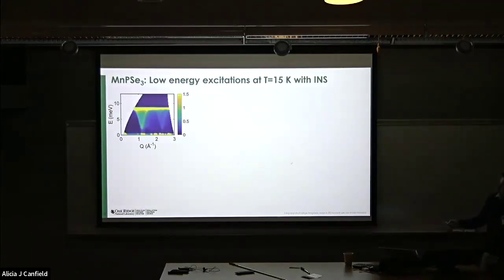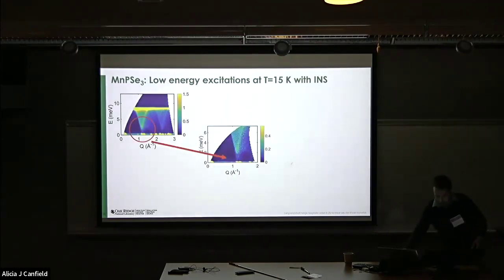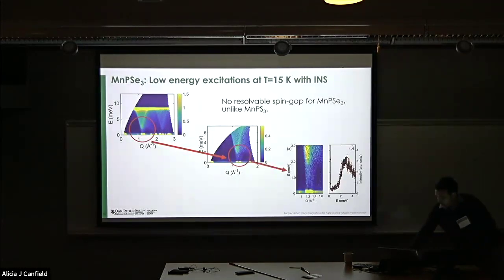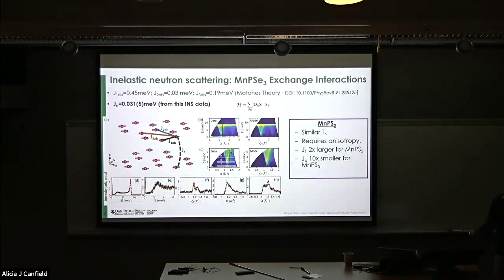If you take the Se3 data and look at this, you think maybe there's a huge gap here, so maybe there's more anisotropy in the material. But if you look more carefully and dig down at the low energy part, you can see there's some dispersion coming out of E equals 0, shown here. Then you're able to model the powder data. You start with theory that predicts the in-plane J1, J2 interactions. You can tune these slightly, and adding anisotropy doesn't do anything.